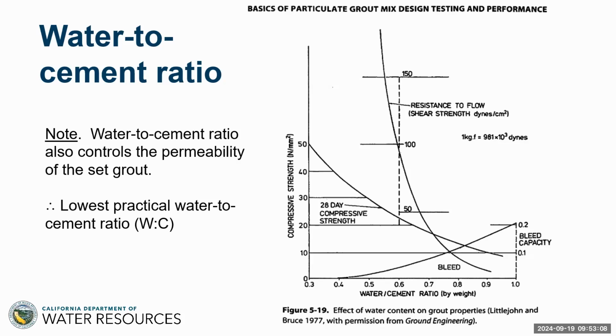So what does the change in water cement ratio do? Well, as we go from 0.4 up to 1, the bleed increases. So that's that graph that sweeps from the axis there up to 0.2. So that means that if you've got a water cement ratio of 1, 20% of that is going to be bleed water at the end of the day. What does it do in terms of strength? Well, there's the 28-day compressive strength. And you can see that as you increase your water cement ratio, you reduce the strength. Strength of water is practically 0, as you know.